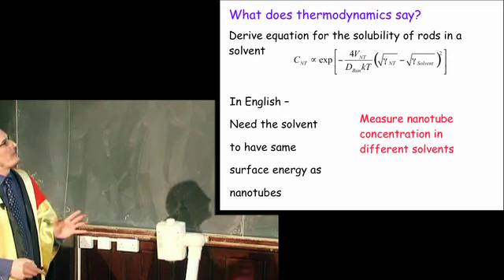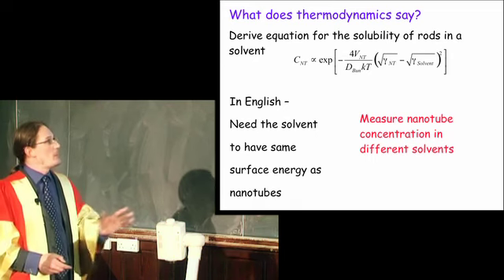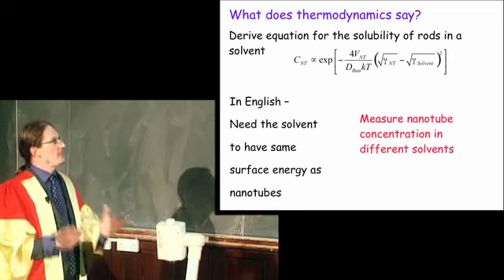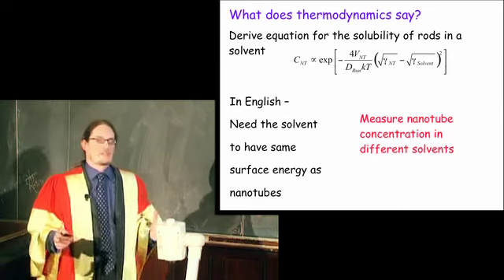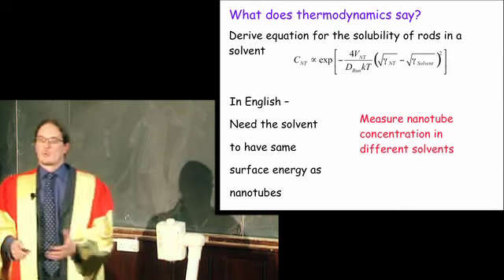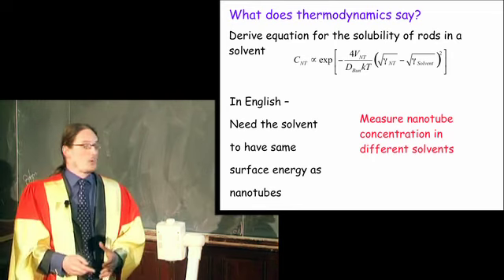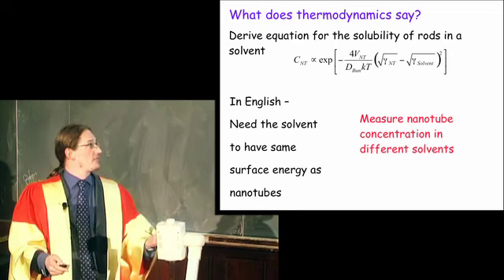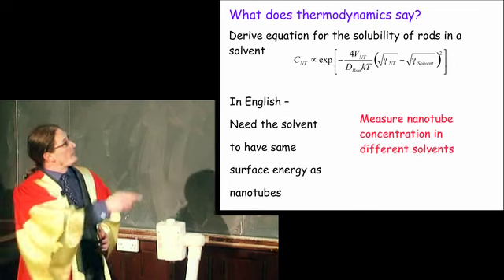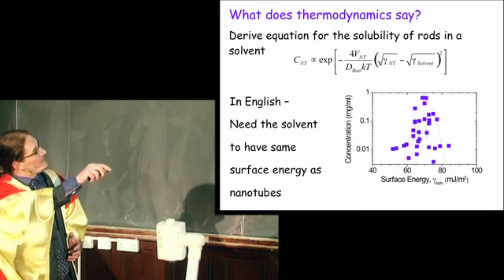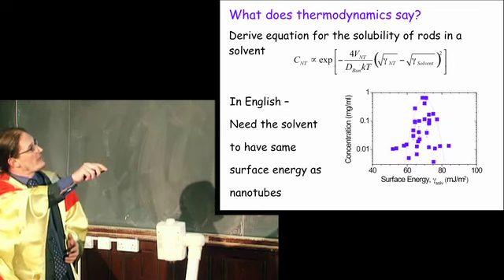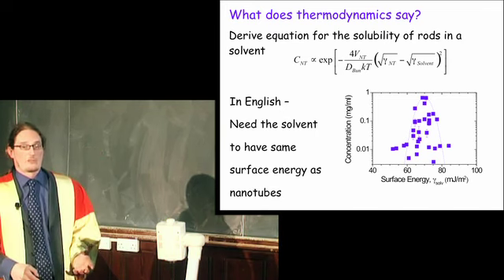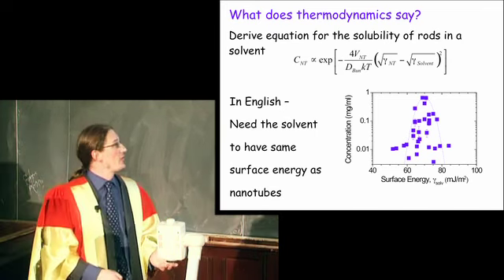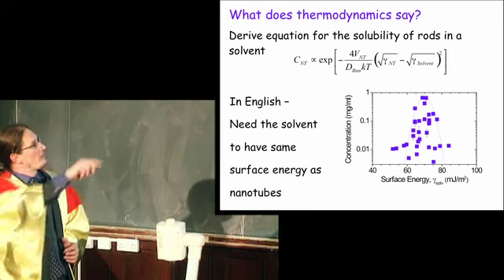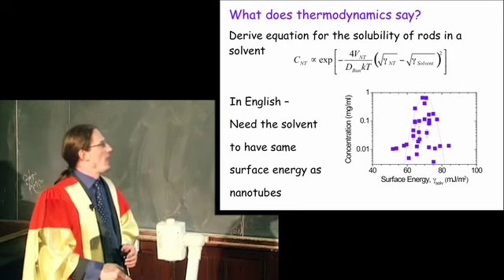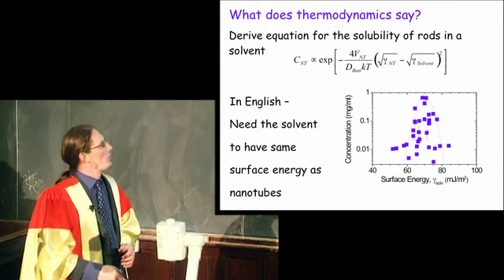So that immediately suggested, theory tells us this, we can design an experiment to test that. We can sonicate nanotubes in a wide range of solvents with a wide range of surface energies, and we can measure how much nanotubes get dispersed and see is this equation obeyed. And as you can see, the solid points are the data, and the dashed line is what the equation predicts, and we get pretty good agreement. Now, there are data points under the line, and it's well understood why that happened. I won't go into it.